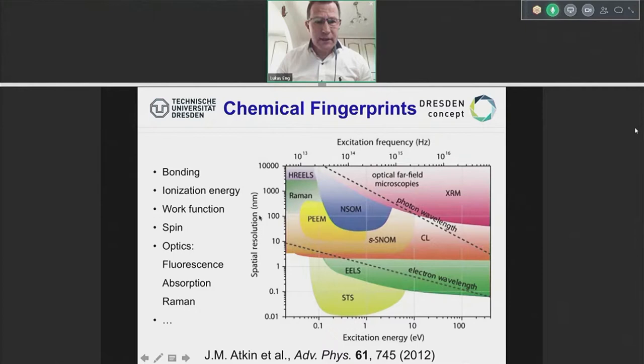And you can see on the left scale that the spatial resolution really goes down. And still today, this is far unique in tunneling spectroscopy, tunneling microscopy, that you really achieve chemical sensitivity on that length scale. You'll find here near-field optics, and that part here, you see not as good resolution as the tunneling microscope. We don't find AFM at all in this cartoon. AFM is somewhere here, and you will see actually we can also show that we get quasi as good as tunneling spectroscopy resolutions.